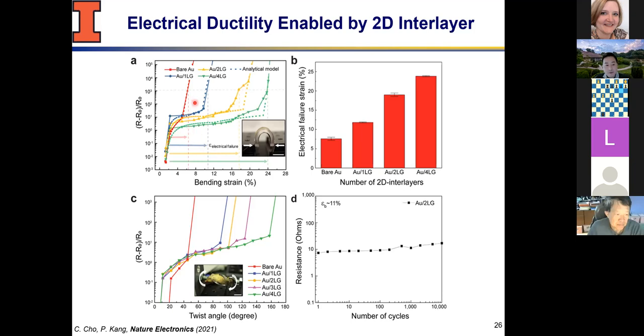And you can define the failure strain by a way. In our case, just to be fair to our calculation, we keep it at 10 to the 3 increase. So it's about kilo ohm. In this case, you started from 1 ohm because the graphene's resistance was about 1 kilo ohm. So we want to make sure that doesn't play a significant role. That was why we cut it there, just to compare these numbers.